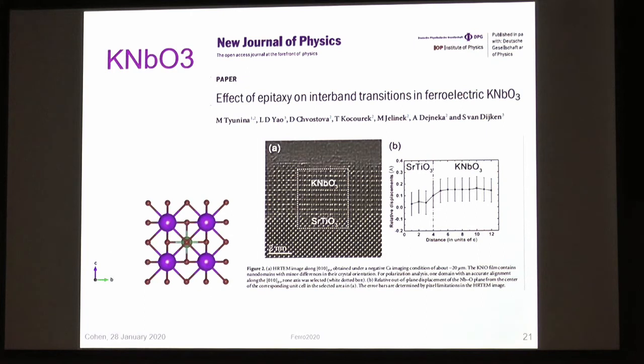Potassium niobate is one of these cases where it seems like you would not get a zero polarization when you compute the polarization, even for a rigid ion model, because the surfaces are charged. So you have, like, potassium and oxygen on the surface. There's no way to make that charge balance. However, people grow beautiful potassium niobate films with beautiful surfaces. So how can that be if it's so unstably charged? It must not really be charged.